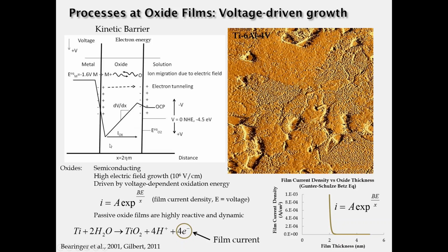But what happens in that few nanometers of oxide is very important. First of all, there is a very high electric field that is generated because of the passive semiconducting nature of this oxide. Metal ions want to react from the metal, and they build up along this interface, and then electrons tunnel through the oxide and are grabbed by oxygen. So you wind up with a positive charge on one side of the oxide, a negative charge on the other, and that's what gives rise to a very high electric field. These fields are on the order of 1,000,000 volts per centimeter. And this is the force that drives the positive and negative ions through the oxide and drives the growth and reformation of the oxide when it's disrupted.